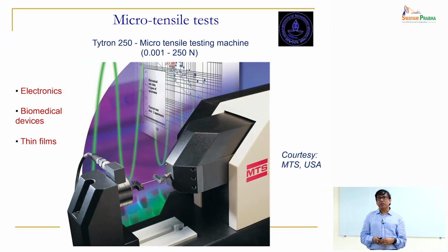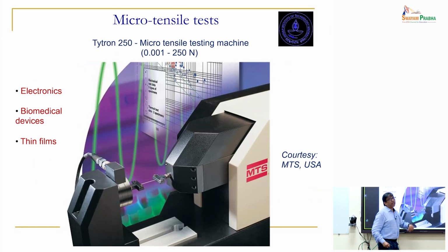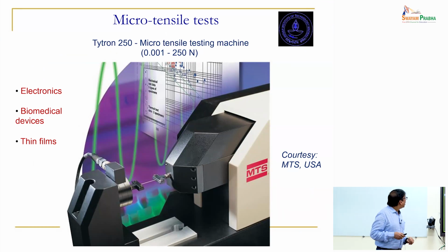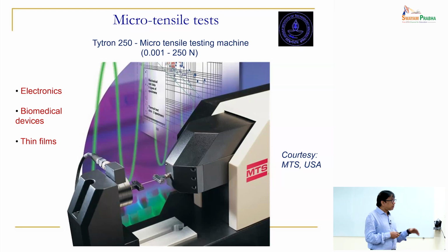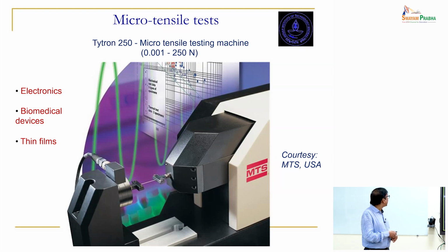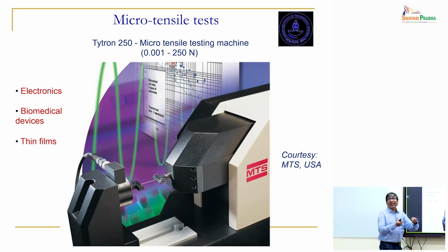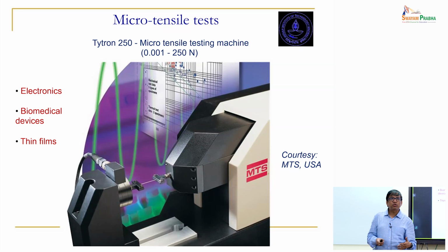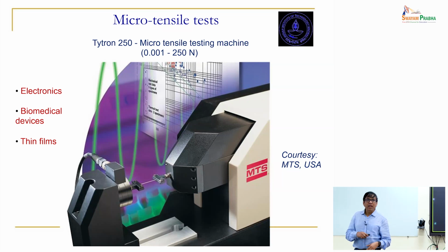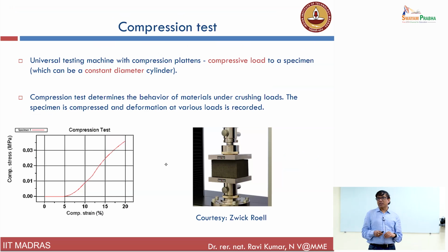But many times in ceramic samples, we also deal with very small sized specimens, and then you really have to go for micro tensile tests or micro scale machines. In fact, I already told you that you first need to know what kind of samples you deal with, so that you can accordingly select the capacity of the machine. In this case, the capacity of this machine varies between 0.001 to around 250 newtons. It's from a company called MTS, but there are other companies which can provide this too. These kinds of testing machines are typically used for thin films where you require extremely low loads, or even materials which you may use for biomedical devices, or electronics that you want to test. But anyway, coming back to compression tests, which are more relevant